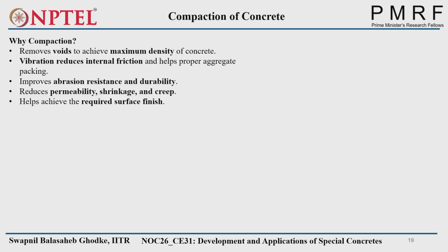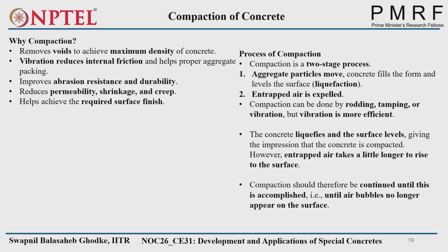Obviously, when voids get reduced, it will reduce permeability, shrinkage and creep. Shrinkage: no voids, so there is no movement of water, so shrinkage cracks will not be there. Creep: if the concrete structure is very dense, the constant load coming continuously will be borne perfectly by that concrete structure, and it helps to achieve the required surface finish.